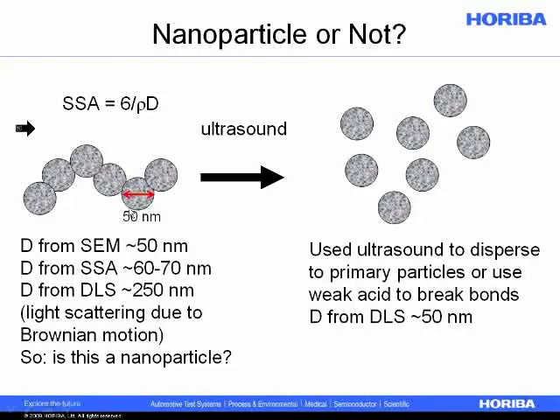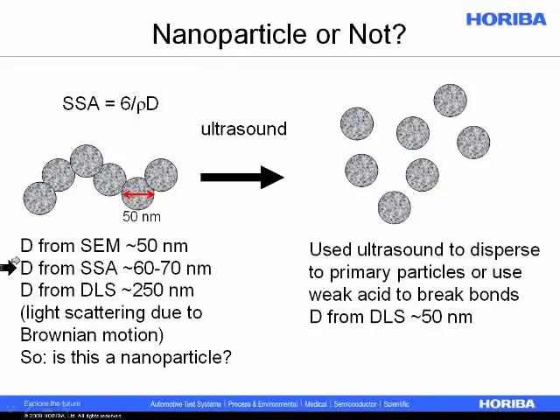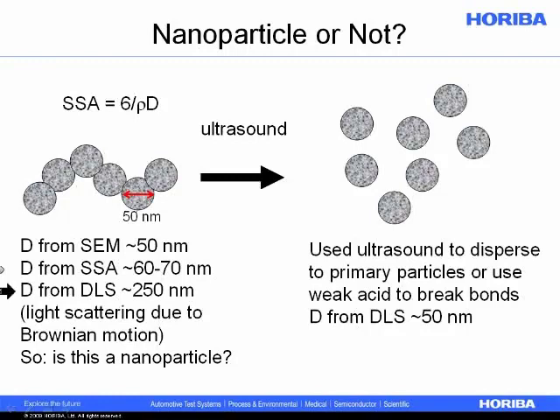If I were to measure the surface area of these particles, only a small part of the surface area is at the contact point, so converting surface area to mean diameter using the standard equation, the diameter reported from surface area might be in the range of 60 to 70 nanometers. But if I were to take these particles and measure them using dynamic light scattering — the technique that measures Brownian motion and calculates particle size — the particle behaves as a joined agglomerate, and using dynamic light scattering we would report something in the range of 250 nanometers.